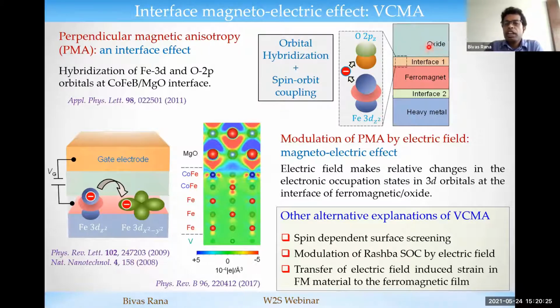When you do so, at the interface, the 3D out-of-plane orbitals of this ferromagnet are coupled with the out-of-plane 2p orbital of the oxide layer. And then a finite amount of electrons is transferred from 3D to 2p orbital. That means there will be an imbalance of the electrons in the out-of-plane 3D orbital with respect to the in-plane 3D orbital. And when you introduce spin orbit coupling in the system, that's how the spin is coupled with the orbital momentum, so then you can induce a finite amount of anisotropy in the spin system.